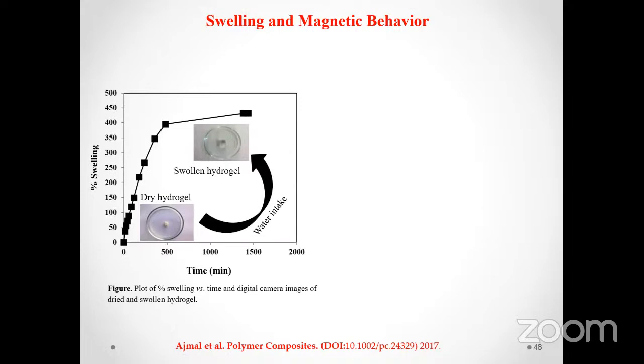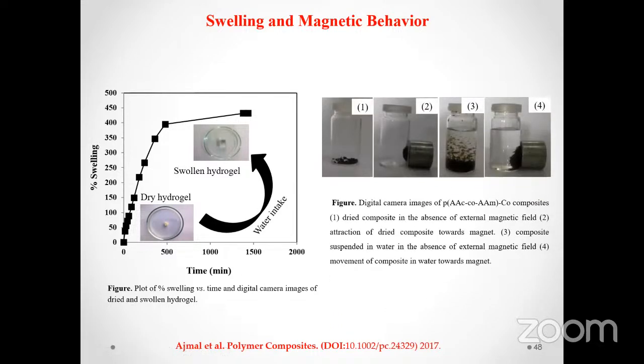So the swelling behavior of the hydrogel was also observed because this was a bulk hydrogel, and we have observed that when the dried hydrogel piece is added in water, it uptakes the water. When water uptake occurs, the hydrogel piece is swollen and its size is increased, and percent swelling was observed more than 400 in this case. And even in this bulk hydrogel, when we have prepared cobalt nanoparticles, they have retained their magnetic characteristics